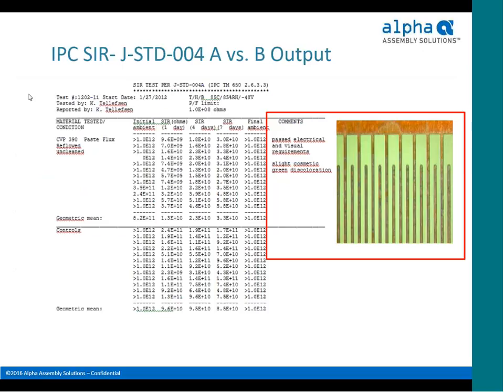So here's an example of the output for the J standard 004A test protocol, where you see there's a number of different comb patterns that are measured on there, and we measure the SIR at initial, 1 day, 4 days and 7 days, and then a final test at ambient. So we get a relatively limited set of data, but we can see all the data here is above 10 to the 8th, so it passes the requirements. There's also a visual requirement as well to ensure there's no corrosion on the test coupon.